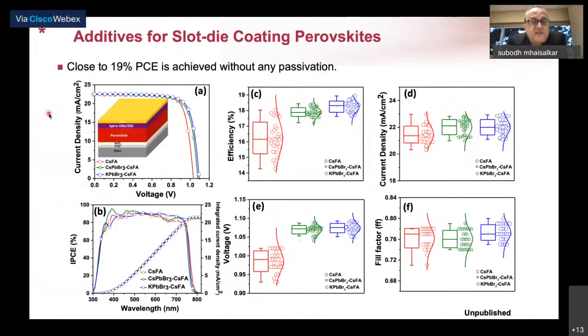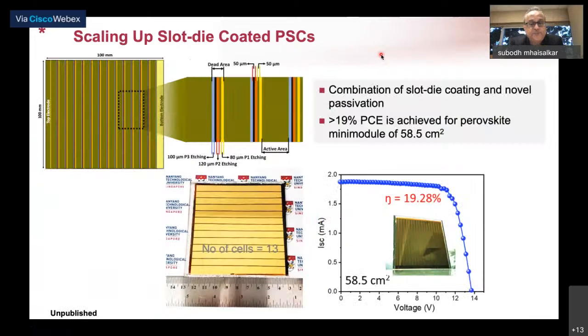Similar to what we have done with evaporated materials, we also had to work a fair amount on the optimization and the additives that would go into the slot die coated devices. As you can see here, we had to take care of compensating for materials like cesium, FA, and potassium, which, just like in evaporated perovskites, also seem to play a role. And consistently, I think we can get efficiencies in excess of 19%.